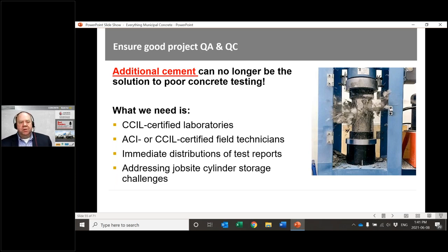So from a concrete producer standpoint, we just don't want to run into potential test result failures. So it's simpler just to over-design the mix and avoid problems. So ultimately, that's not a solution that's going to work in the long term. So again, we need to have properly trained people, CCIL or ACI certified people out in the field doing the testing. We need to have good distribution of test results so everybody knows what's going on. And we need to address things like cylinder storage at job sites to make sure that we're properly evaluating the product. Then the concrete industry can dial back that over design that we have in the mixes, but that could have a big impact.